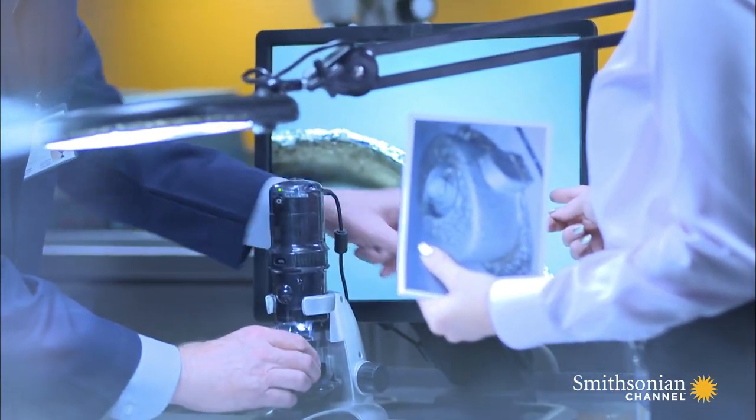It's no wonder it cracked. We're only talking — it was 0.35 millimeters in thickness. It's a couple of sheets of paper. Investigators study the manufacturer's report and learn why one side of the stub pipe was so dangerously thin. It was due to a manufacturing error.